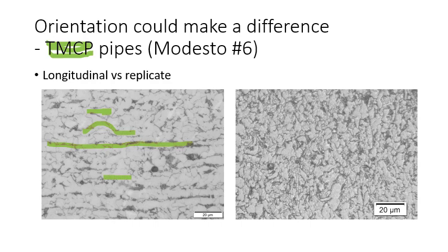That can lead to a difference between the longitudinal direction destructive microstructure and the surface replica. When we look at the surface replica on the right, one thing we notice right off is that the second phase, the dark phase, isn't as distinct as it is in the destructive microstructure. So that's going to be a little bit more of a challenge for our assessment methods.